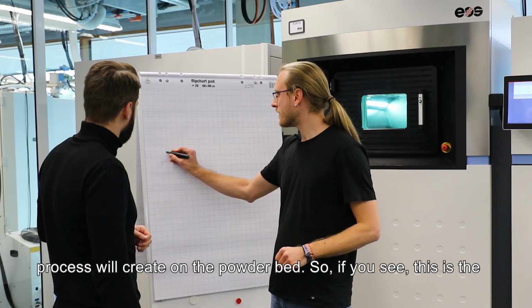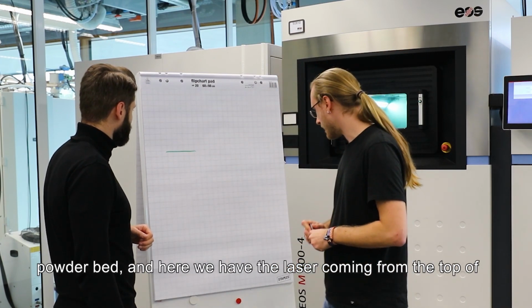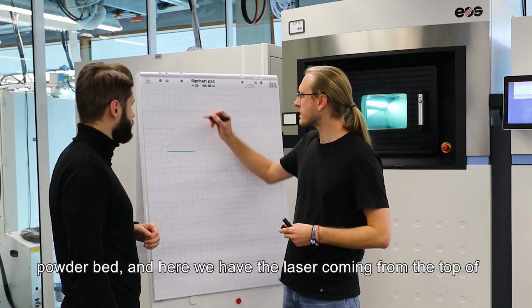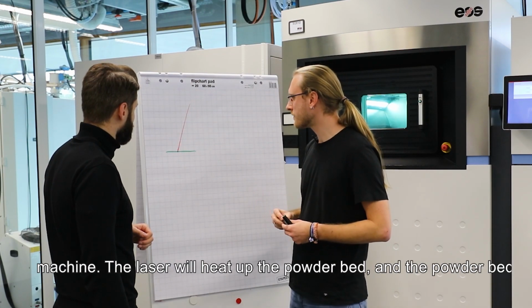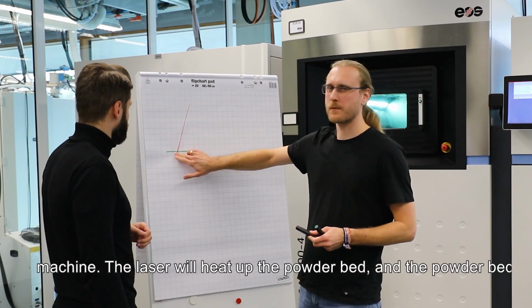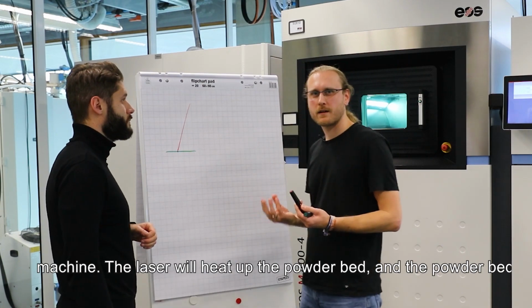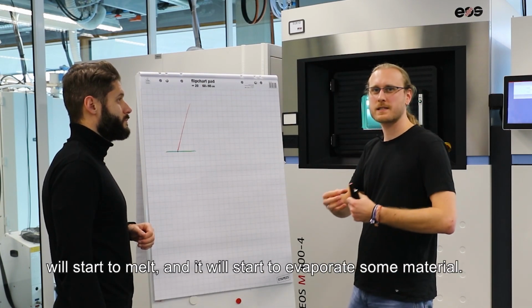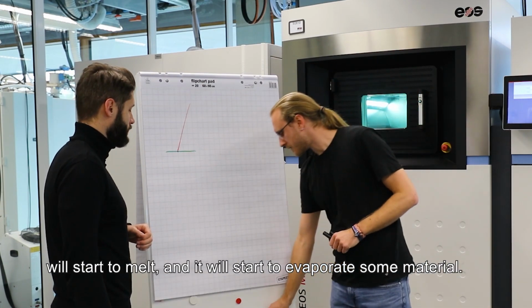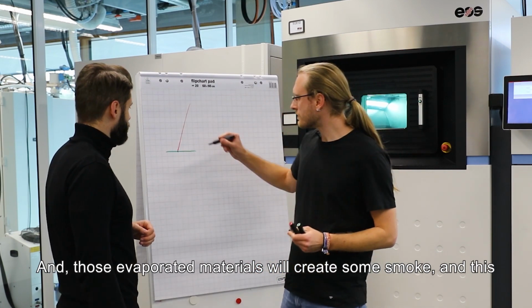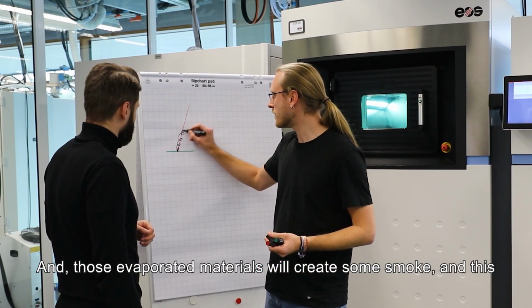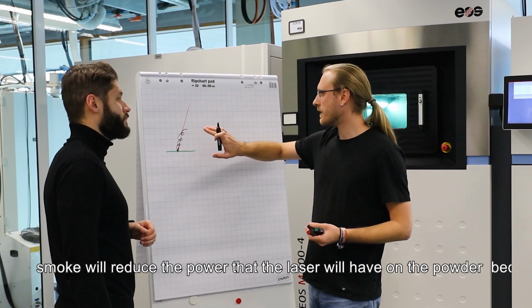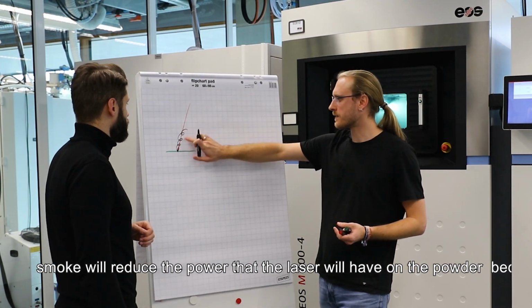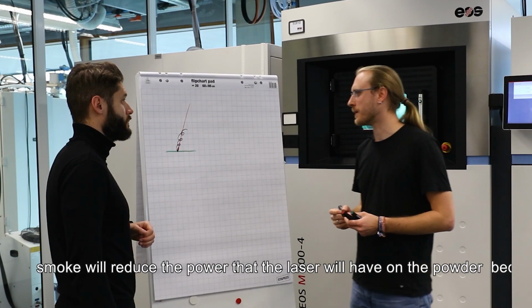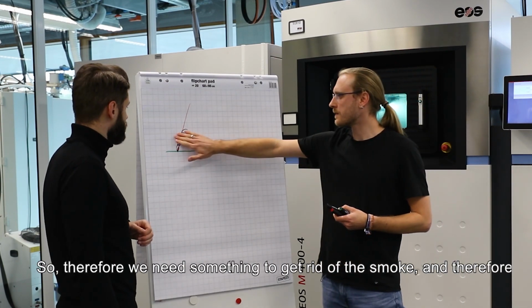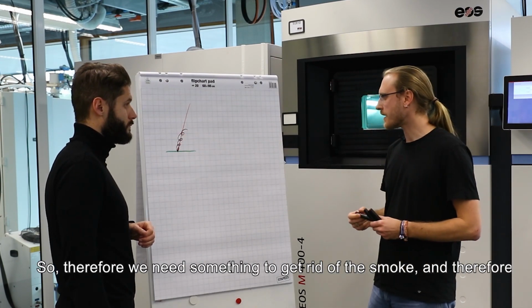So if you see, this is the powder bed, and here we have the laser coming from the top of the machine. And the laser will heat up the powder bed, and the powder bed will start to melt, and it will start to evaporate some material. Those evaporated materials will create some smoke, and this smoke will reduce the power that our laser will have on the powder bed. So therefore we need something to get rid of the smoke, and therefore we need some gas